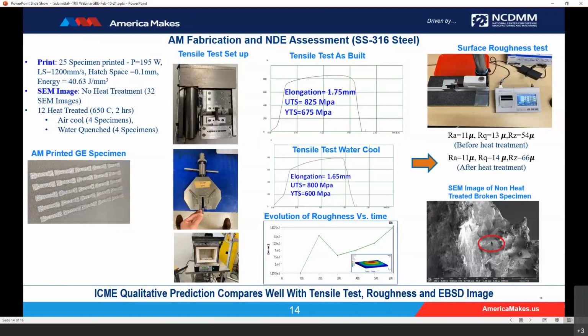We were able to not only test these and collect the data, but also to see the impact of the quenching, cooling, and all the various applications on the tensile test behavior, the stress strain curve, and the performance of the materials. Not only did we measure tensile test as built, tensile test water cooled, you can see there's slight variations. Again, more testing needs to be undertaken. We need to translate what we learned virtually and correspond to what we will find through physical experimentation to update our knowledge and update our solution.